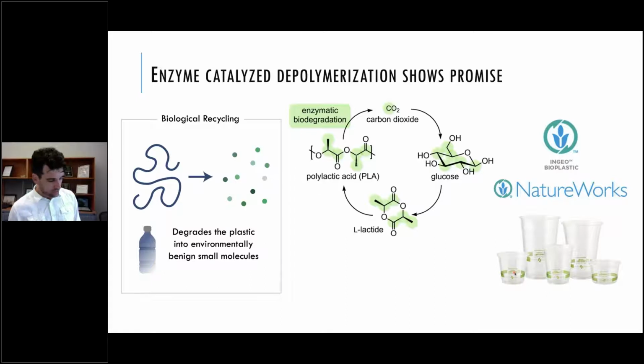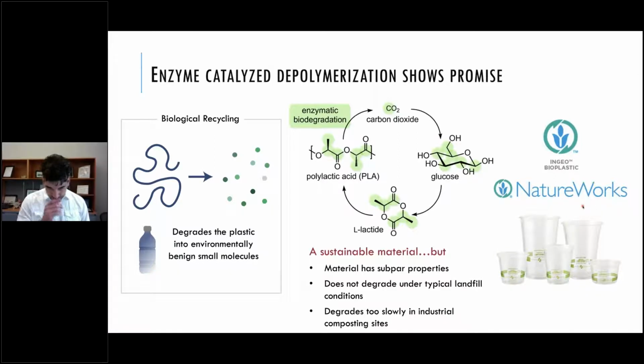So again, these ideally can be composted and eventually degraded and metabolized back down to CO2 and water. That obviously can be used by plants to reform glucose, and we get polylactide by the fermentation through engineered bacteria of glucose to lactic acid and eventually the monomer lactide that can be repolymerized to polylactic acid. So again, this is a commercial product made on, I think, hundreds of thousands of ton scale per year by NatureWorks, which is a company with facilities in Nebraska. I think the company's based in Minnesota.